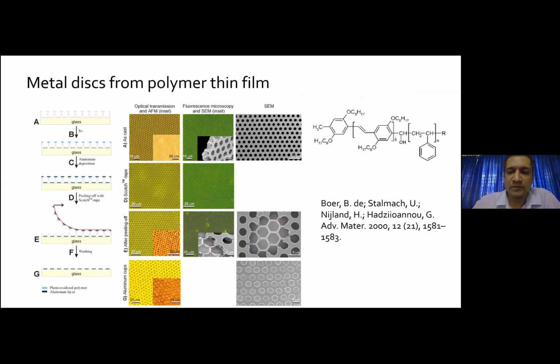So the de Boer group first made a breath figure onto the surface of the glass using the polymer as shown here. This is the block copolymer, and you have this octyl side chain, octyloxy, and then this is an octyloxy polyphenylene, and then you have the styrene. These two are linked to form a diblock copolymer, and the R group is the one which is varied.